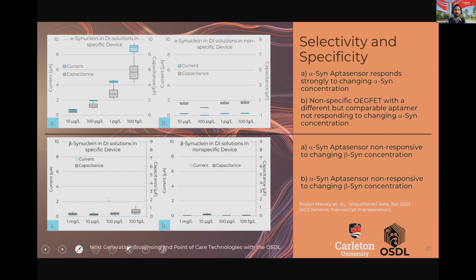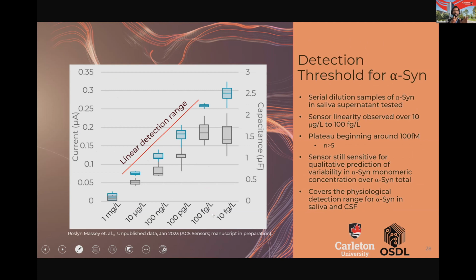So just to reemphasize, we have selectivity. So the device is sensitive to alpha-synuclein, but it's not sensitive if you are looking at alpha-synuclein and the aptamer is not present on the device. Okay, so that's the selectivity from the aptamer. We also have specificity to the analyte. So with the same aptasensor, with the proprietary aptamers, you see that it's not sensitive to anything else in both scenarios, which means that we can rely on a device like this to separate and to quantify the total alpha-syn monomer to total concentration in a large linear detection range, which covers the physiological detection range of alpha-syn in saliva and CSF.